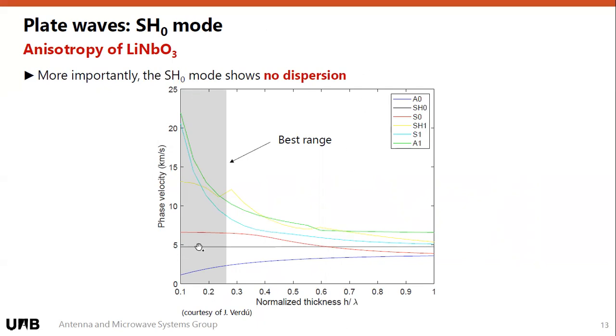And we want to stay in this area below the 25% ratio, because the phase velocity of all other modes are well away from our phase velocity. That means that our structure, when we define the IDT, is going to be efficiently exciting the SH0 mode. It's not going to be anywhere close to defining any lambda half or lambda quarter structure for any of the other modes. So you have no excitation of the A0 mode, no excitation of the S0 mode, because their velocities are way off, one is below and one is above. What is also good about